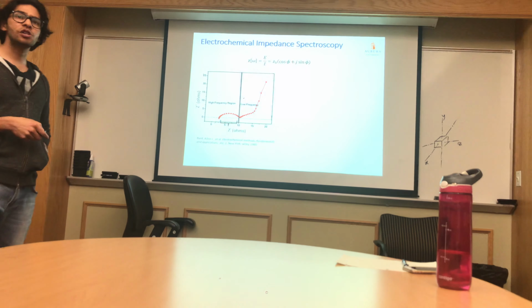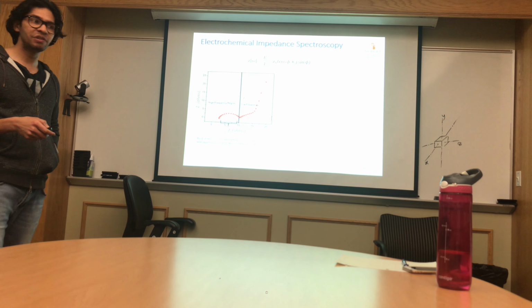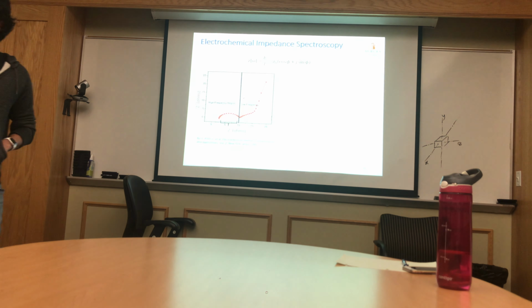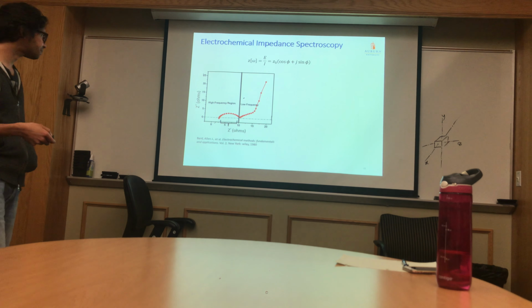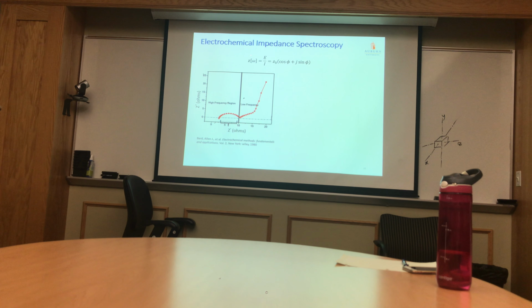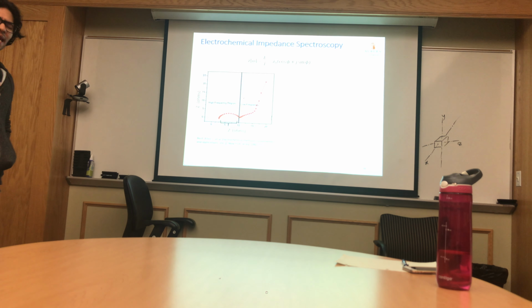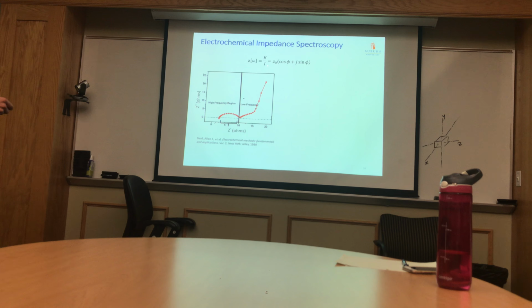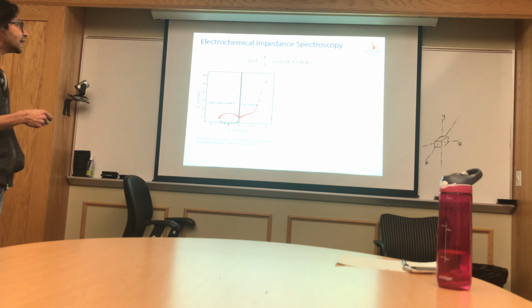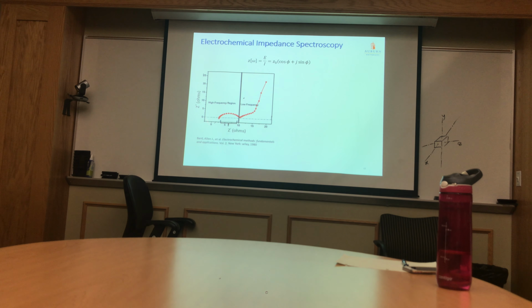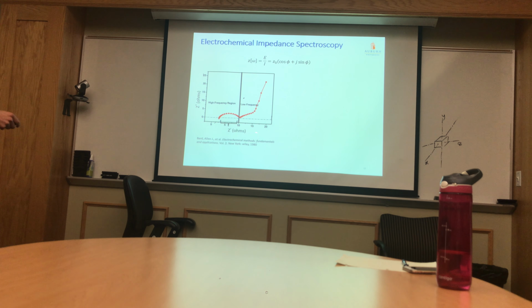Further, we will also perform electrochemical impedance spectroscopy, which will be used to determine the various impedances and resistance in our electrochemical system. In electrochemical impedance spectroscopy, we apply an AC voltage to our sample, and we record the corresponding current so that we can find the values of impedances. So this is a Nyquist plot which we can get from electrochemical impedance spectroscopy. This is the real impedance, this is the imaginary impedance. And from this plot, we are able to determine various